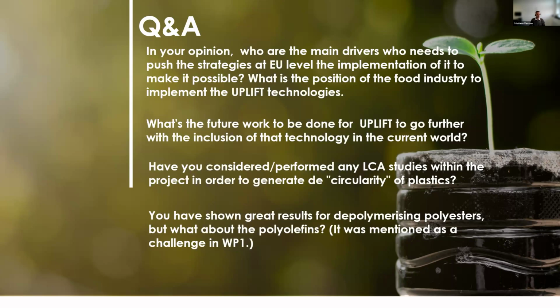But first of all, these processes were way too slow. This was requiring months. And second of all, what our original aim was not just to break down the polyolefins, but to obtain oligomers that were then easier to repolymerize and obtain more cleavable or more recyclable polyesters. And what we were obtaining was low titer of a mixture of different oligomers that were making the recyclability really, really challenging.